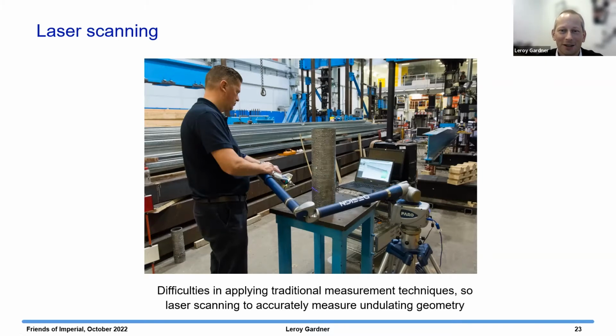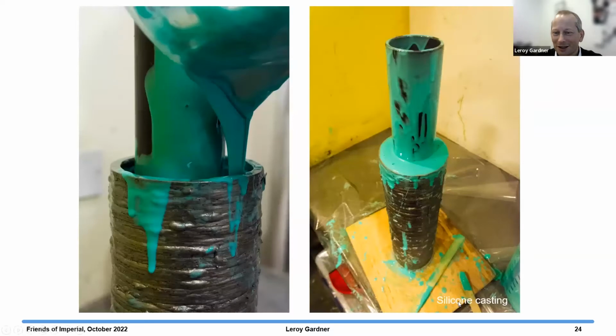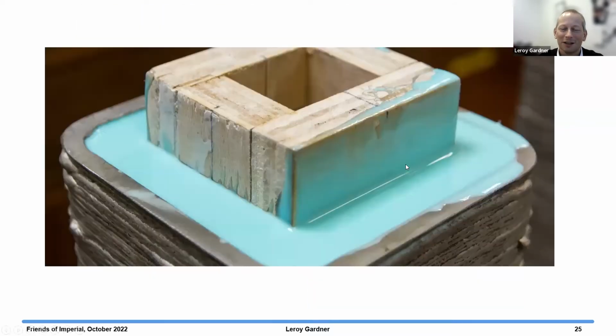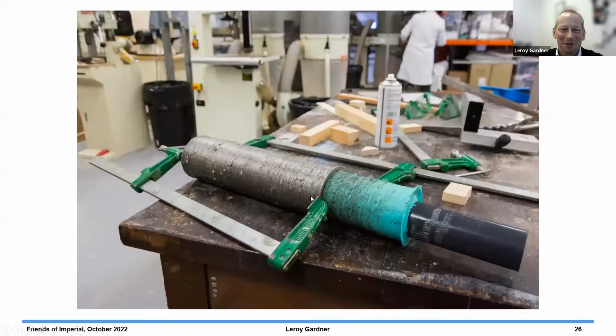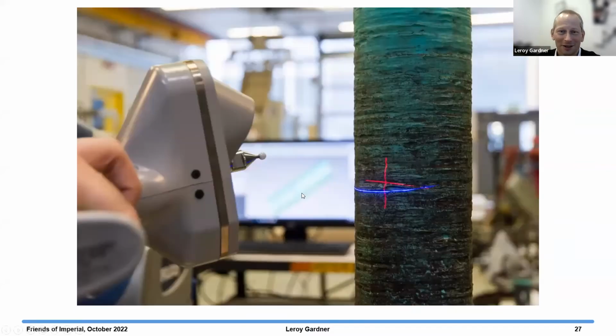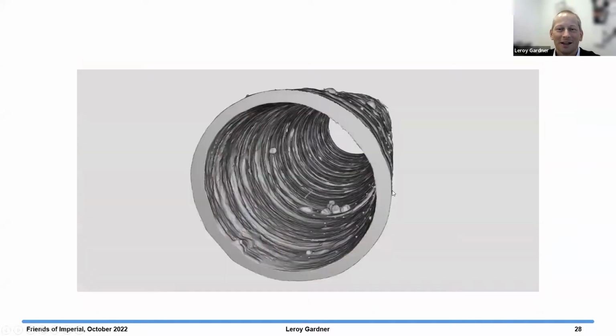So the problem with a tube is you can scan the outside, but it's not so easy to scan the inside. So we had the idea of trying some silicone casting of the inside, a bit messy, but we created a silicone cast, which we got a bit better at pouring it later on. And then we pulled out the silicone cast, having sort of lubricated it and so on, and scanned the cast, and then joined the inside and outside to get a full sort of 3D representation of the sample.